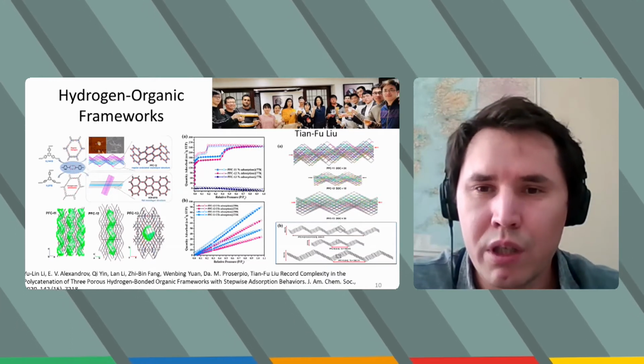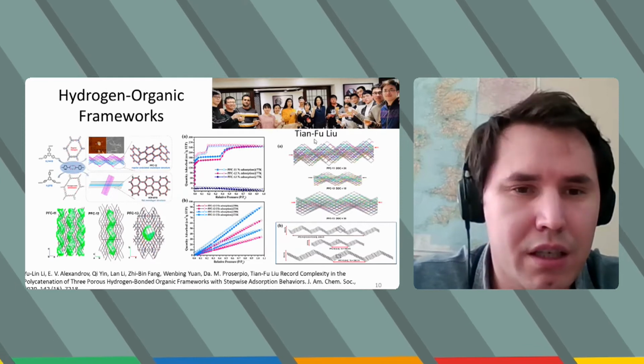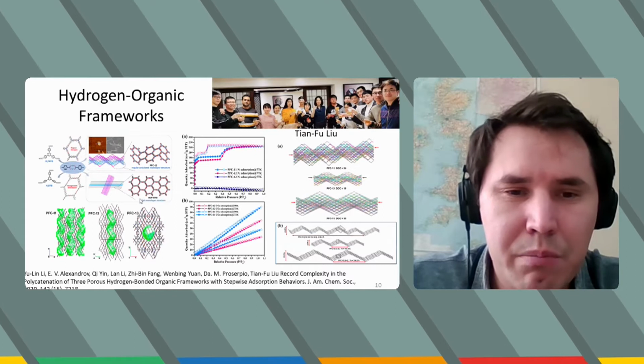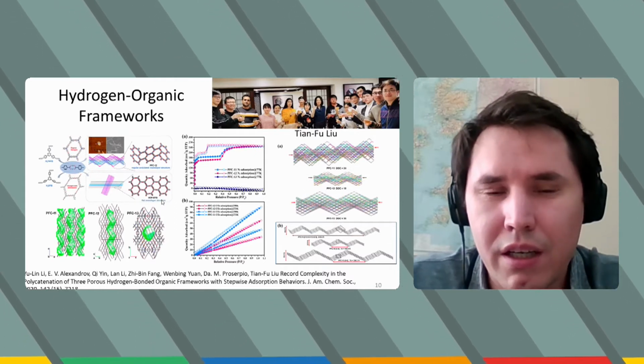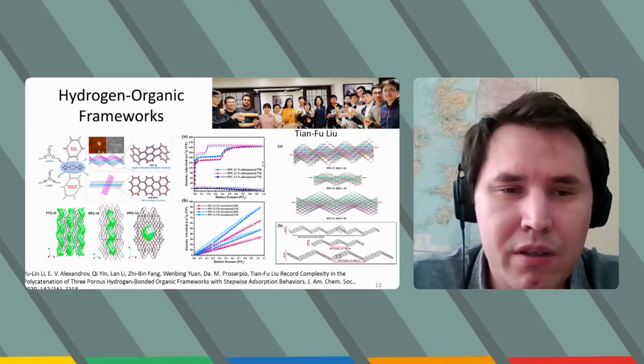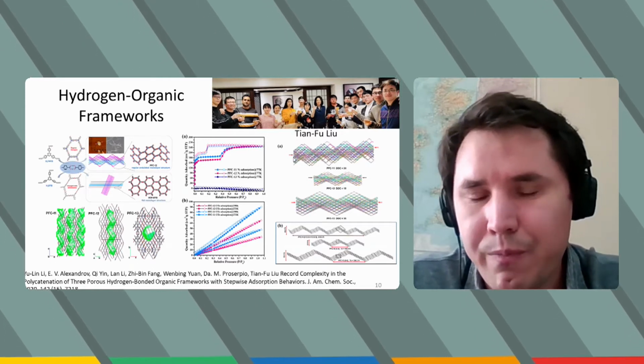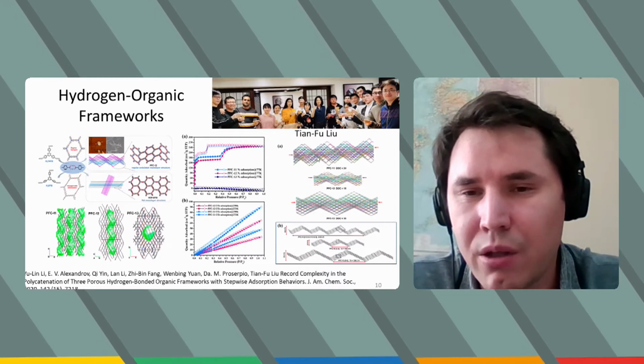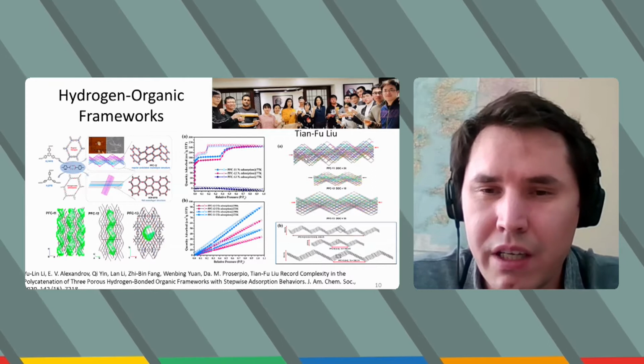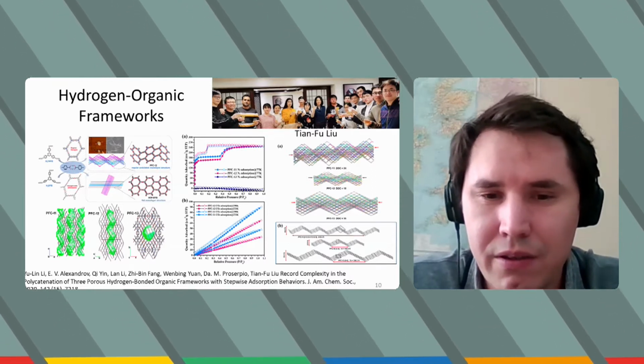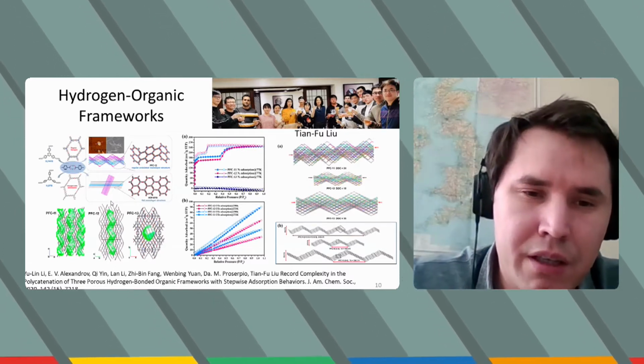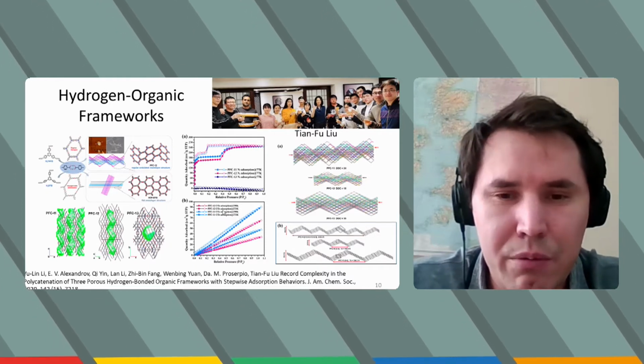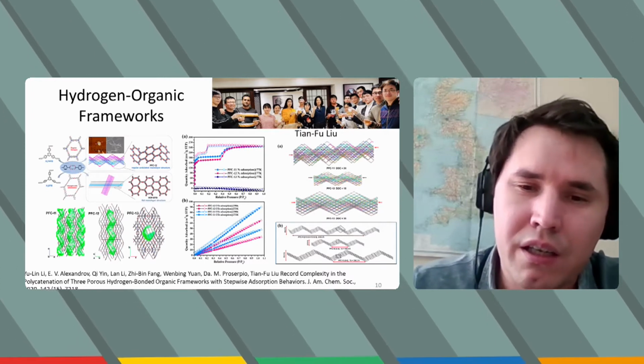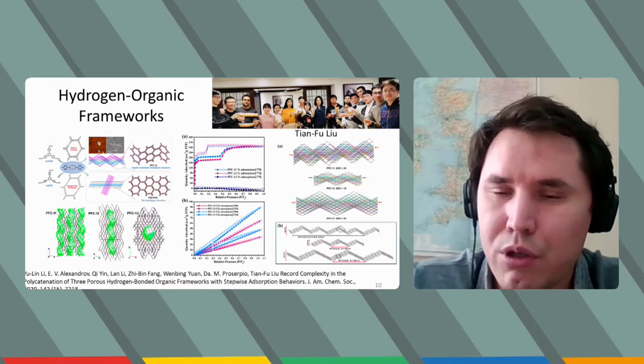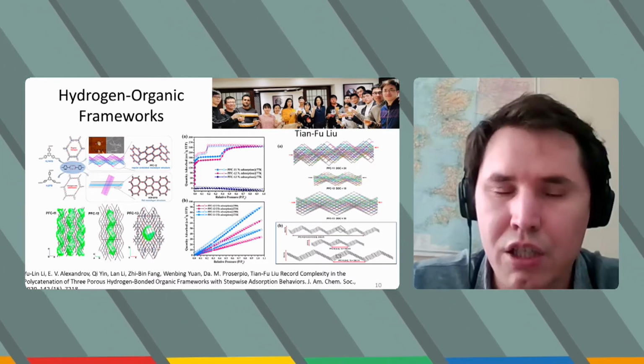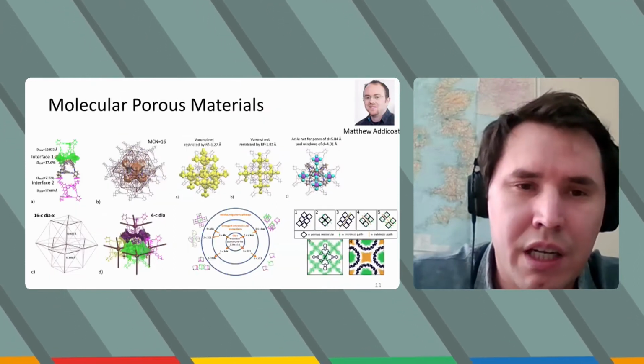In cooperation with the group of Tianfu Liu from the Chinese Academy of Science, it was found that very simple compounds connected by hydrogen bonds can be assembled in a very complex way. For example, 3 new compounds synthesized by the group of Tianfu Liu were shown to be very undulated, and at the same time they produce very peculiar and very complex weavings, and these weavings have record complexity. At the same time, they are still porous, and it is possible to capture CO2, which is the main component of greenhouse gas, and also to capture cancerogenic compounds.